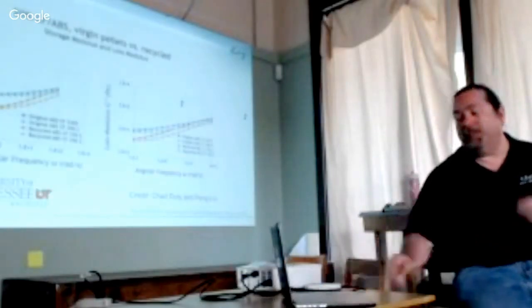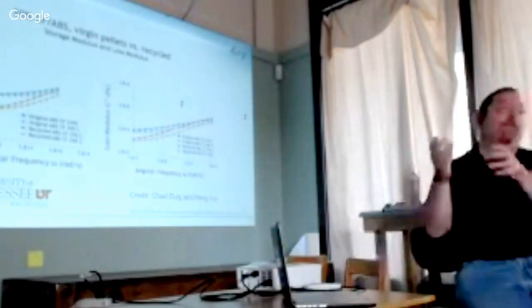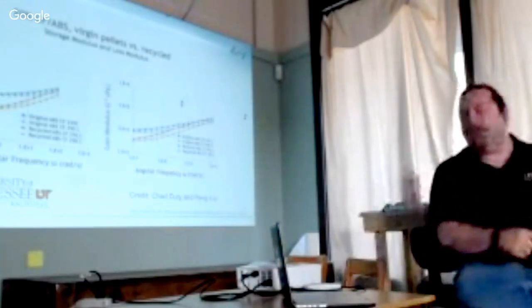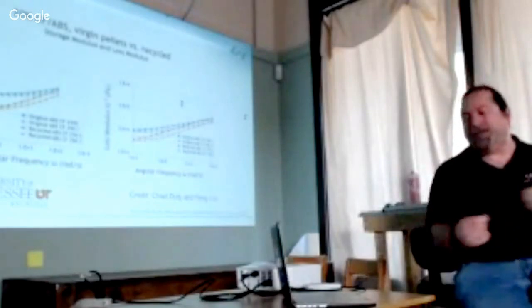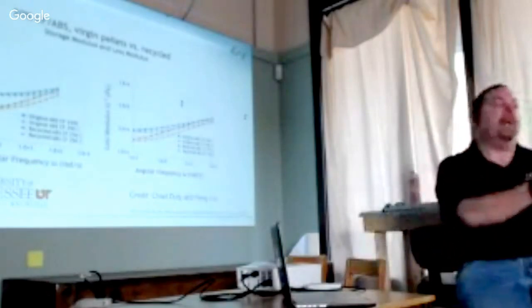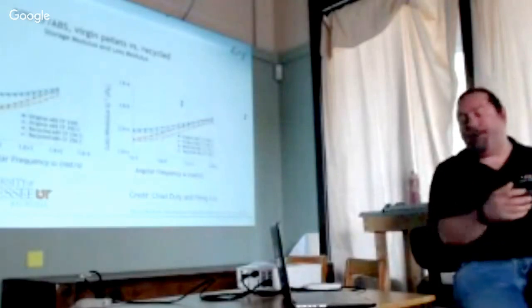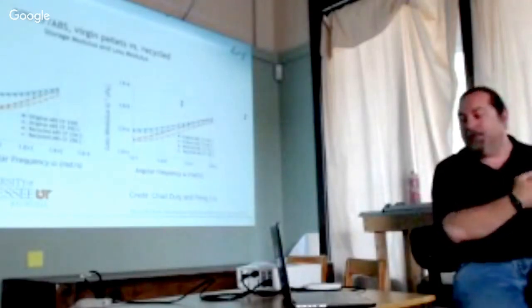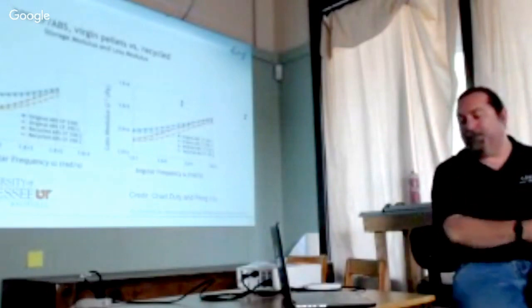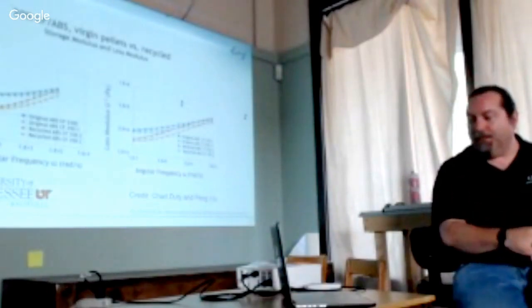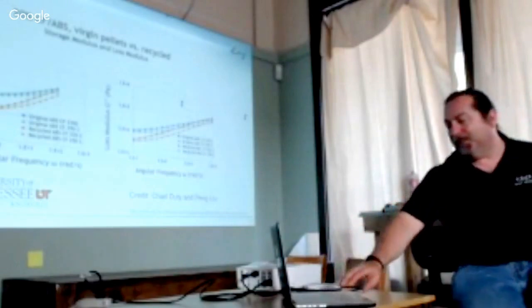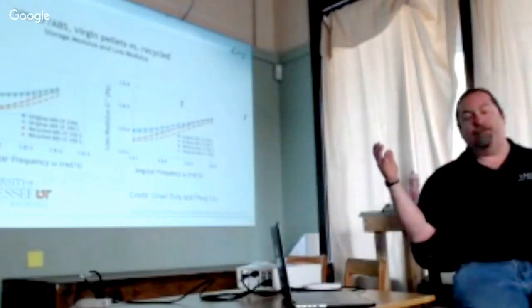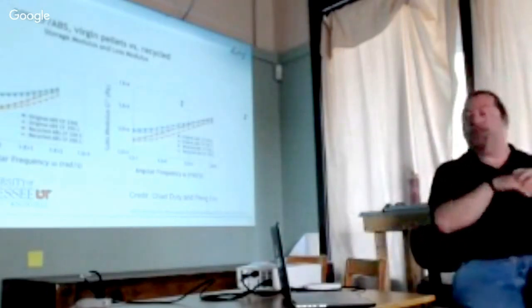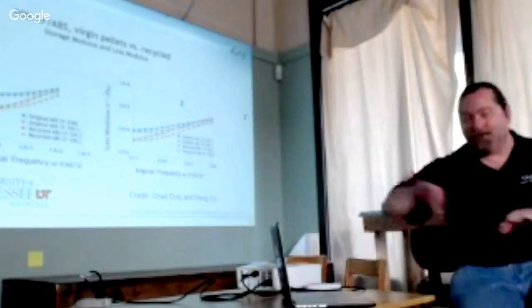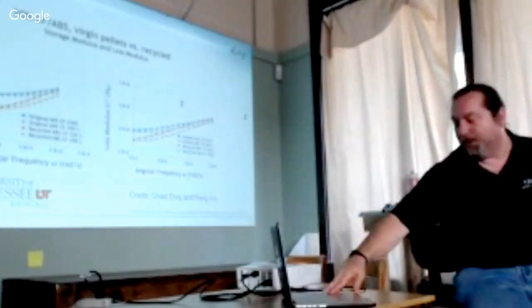Some of the studies, I mentioned rheology. So in this process, the viscosity of the material is very important. The viscosity is a function of shear rate, and that determines how it behaves in the extruder. So we're comparing all these different materials with rheology, and this one just shows the virgin ABS versus recycled. When it goes recycled, it shortens the fibers and reduces the viscosity. So it just shows the viscosity profile after it's recycled.